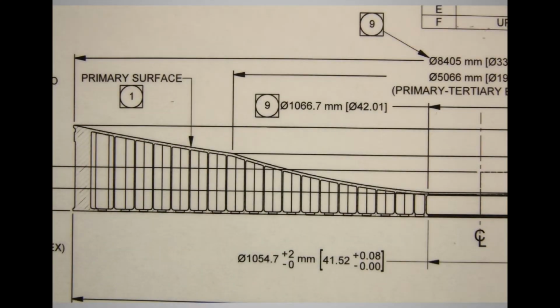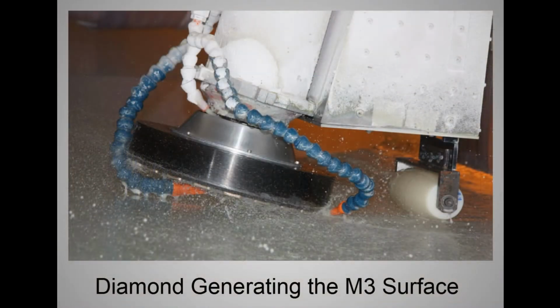Anyway, this is a drawing of the mirror. We cast these mirrors, we spin cast them, right? Well, there's no way to spin cast a double curve, so we spun it for the outer curve, and as a result, the glass in the middle was about 10 to 12 inches thick, so we had to generate that out. That was the first step of the process when we started the front. We have a big honking diamond wheel that we throw lots of mist at. You can see the little pellets there. This is a coarse diamond pellet, about 30 microns, or 30 microgrid, 30 mesh diamonds. So they're about 1 millimeter or so across.